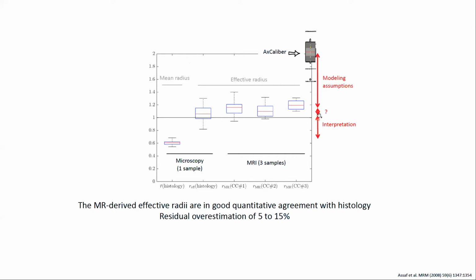But the main take-home message is that interpretation is important. When you compare modalities, it's important to consider what is encoded in those modalities. While microscopy, confocal and electron microscopy, often focuses on the average values of a distribution, we can't measure that. We measure something which is still weighted, which is the effective radius.